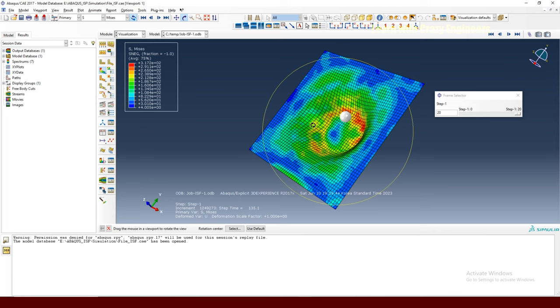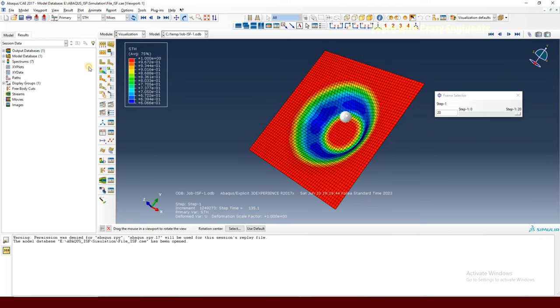So when the sheet stretches towards the forming depth, it always causes thinning that you can clearly see in the sheet thickness changes. So you can see this is 1 millimeter, and in the unformed region, this red color, it has 1 millimeter. But in other cases, you can see there is a thickness change. This happens because of the bending and stretching towards the forming depth.